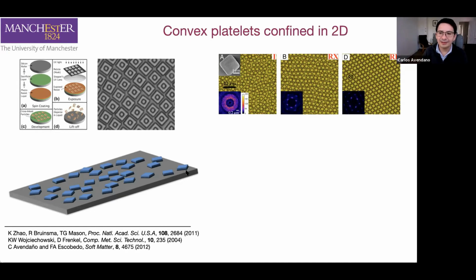But at intermediate concentrations, what they observe is the formation of a random hexagonal phase. So you look at the center of masses of these squares, they are localized in a hexagonal lattice. But the particles can adopt any type of orientation within the plane.